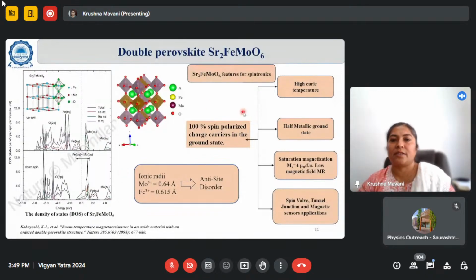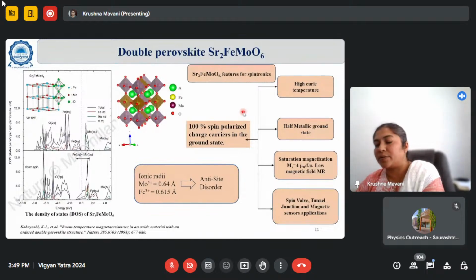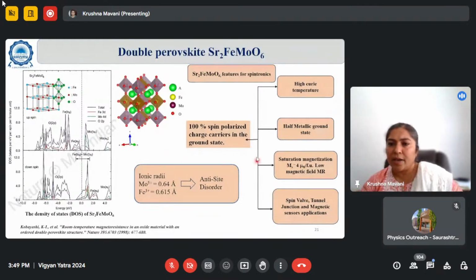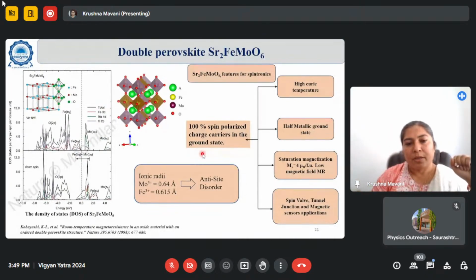So what are the different features of this double perovskite? You have a high Curie temperature, half metallicity, saturation magnetization of this value, and these are the applications of this material. The most important feature is that it is predicted to have a 100% spin polarized state at the ground state because of these two channels, one having a gap, one without a gap. Because molybdenum and Fe ions are of similar size, you also have this problem of anti-site disorder in these materials.